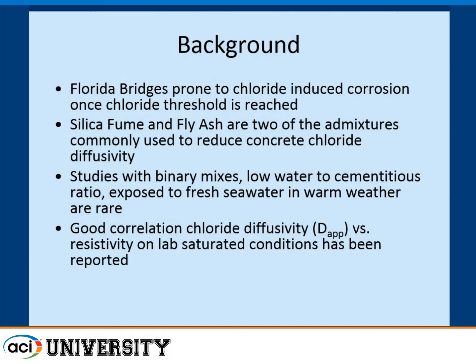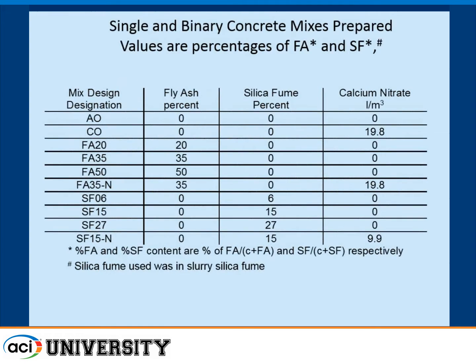reduce the chloride penetration. In this particular study, we are going to be talking about binary mixes. So we look either at the fly ash effect or the silica fume effect in different amounts. And we did the test in fresh seawater, with outdoor exposure in South Florida. Also, something that has been reported is that there is a good correlation between chloride diffusivity and resistivity from laboratory measurements.